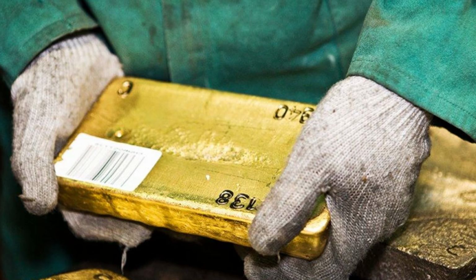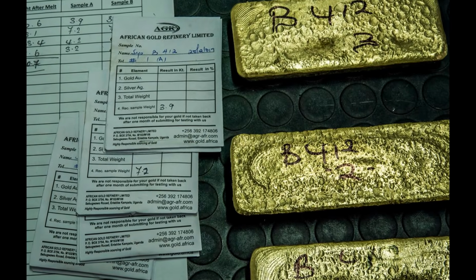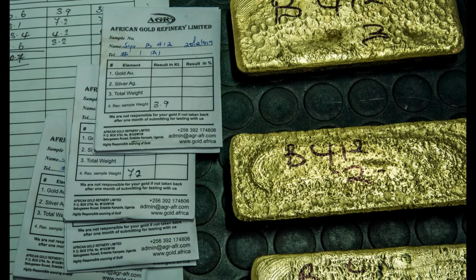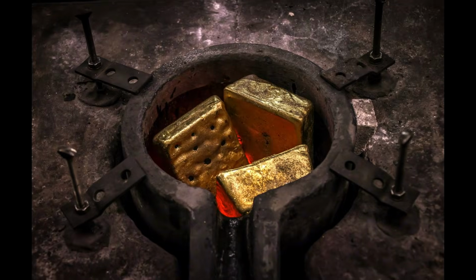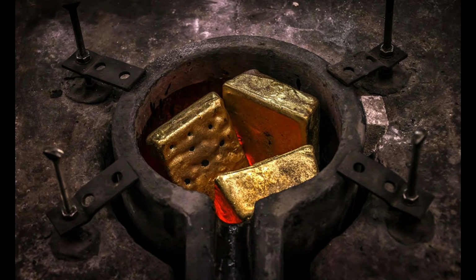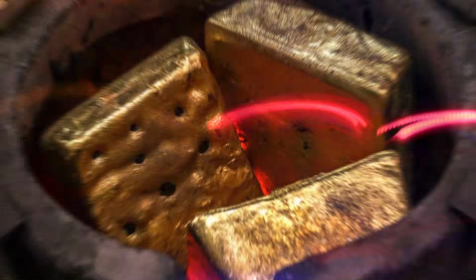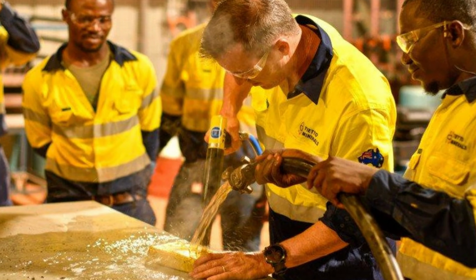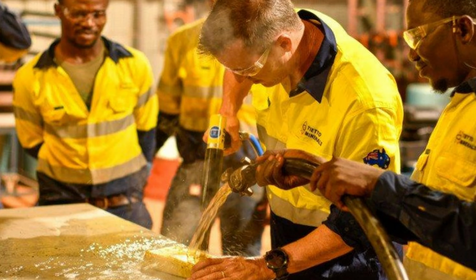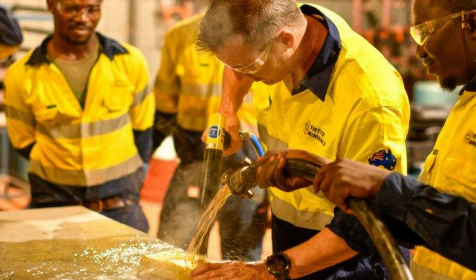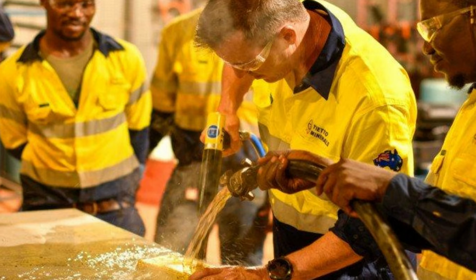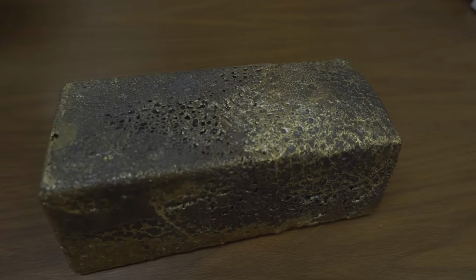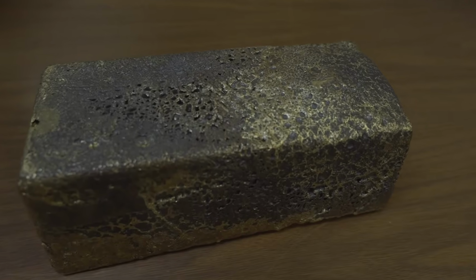The incoming bar is weighed. Its documents, seal, markings, supplier, and lot number are checked. Yet taking a random shaving from one corner may not reveal the true composition of the whole bar. Dore is an alloy, and an imperfectly mixed alloy may contain local variations. Surface contamination can also distort a careless test. When large amounts of money depend on a tiny sample, that sample must represent the entire lot.